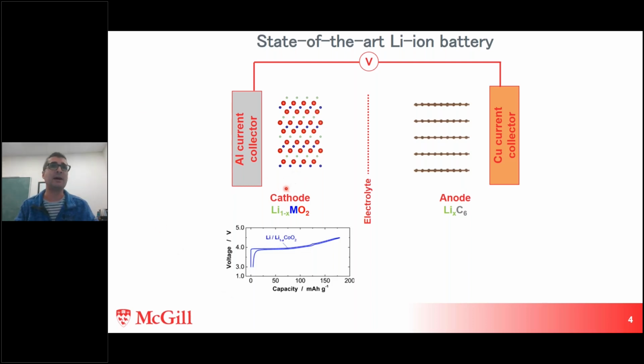So in a lithium-ion battery, we have a cathode, which has lithium in it when we make it. So it's usually a layered oxide. And I'm going to talk about the layered oxides for sodium ion as well. So basically, I have a layer of lithium, layer of oxygen in red, and then a layer of transition metal. So for lithium ion batteries, this historically was a lot of cobalt. Now we're transitioning towards nickel with some manganese, but we still have those elements that are a sustainability problem and a price problem because the abundance is so low that the price just fluctuates like crazy.